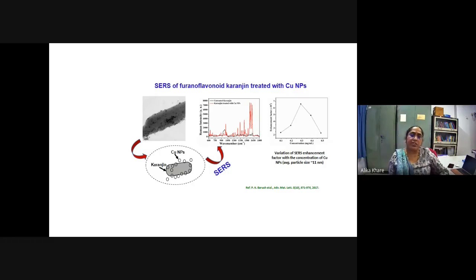We just took this crystal and poured the suspended solution which I showed earlier, which was synthesized with the help of the laser focusing onto the copper or silver target in the liquid. And then we tried to record the Raman.